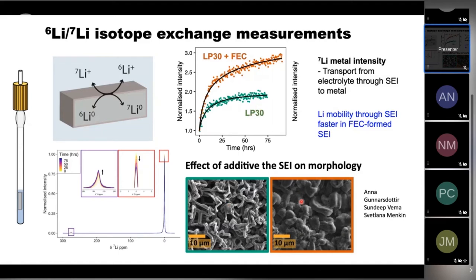And that has a dramatic effect on the nature of the dendrites that you form. So this is the dendrites that you form with a normal electrolyte, and these are the much flatter and more homogeneous ones, with lower surface areas, that you form with FEC. So we're trying to understand both the mechanisms by which dendrites form, but also then how we can improve and try and mitigate their formation.